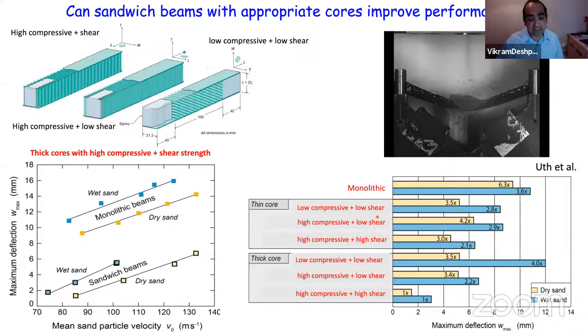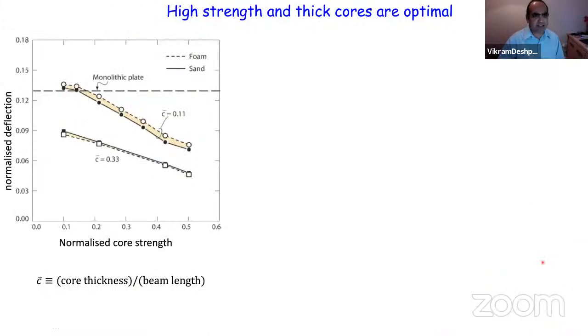are what you need for this kind of an application. So in this particular case, high strength is extremely good, basically. And you need thicker cores rather than thinner cores, and they will help. Though, of course, you can see here that in some cases, thick cores, if they're very badly designed, can do rather badly. Okay, so use then the simulations to really try to understand why is this the case?